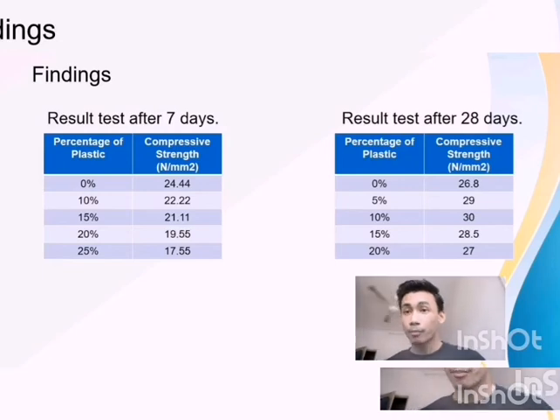So it can be shown that a lower percentage of plastic, around 5 to 10%, will produce a higher compressive strength of the concrete. It can be shown that the pros of replacing fine aggregate with plastic is that the plastic really gives the concrete a higher compressive strength than the natural concrete.